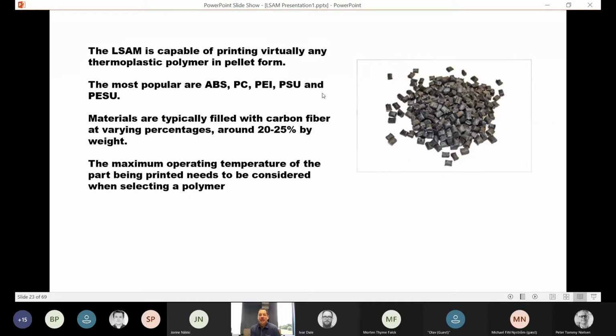Speaking of that, the LSAM is capable of printing virtually any thermoplastic polymer in pellet form. The most popular that we've come across are ABS, polycarbonate, PEI, PSU, and PESU. These materials are typically filled with carbon fiber at varying percentages, usually around 20 to 25% by weight. The maximum operating temperature of the part being printed needs to be considered when selecting a polymer.